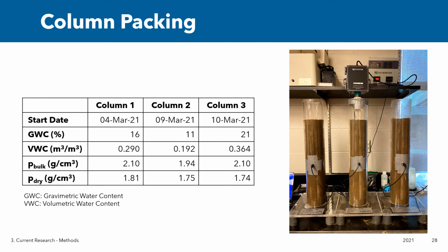For the column experiments, column 1 was packed at the optimum water content, column 2 was 5% less, and column 3 was 5% more to achieve a range centered around the optimum. Once the tailings and water were mixed, they were packed to try to achieve a density of 95% of the Proctor maximum. Immediately after the columns were packed, the oxygen sensor cap was placed on the column for 24 hours to monitor the initial oxygen consumption. Oxygen consumption tests then occurred weekly, and outside of the 24-hour test period, the columns have been left open to the atmosphere. TDR probes were also placed in the middle of the column to monitor water content changes.